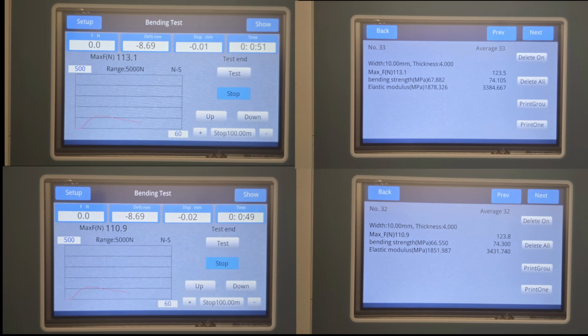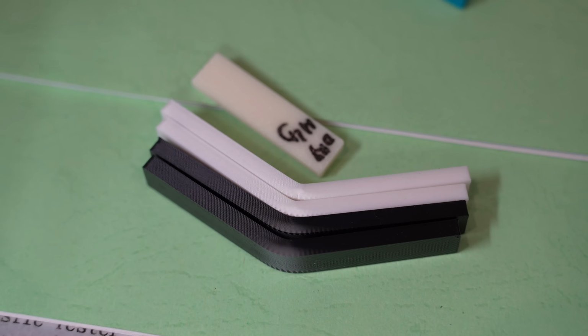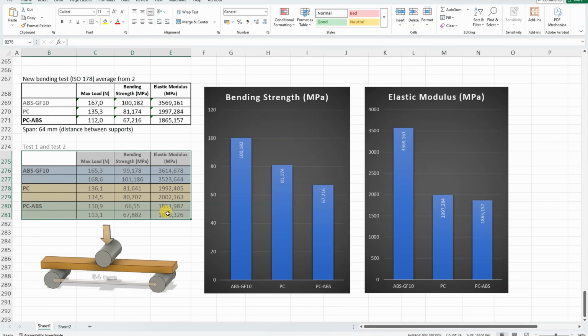And here you can see the maximum load, bending strength and elastic modulus, but also the graph of the break. Similar values from two measurings. These are measured numbers, this is the average from two. They're very close to each other, so in the future I will have only one test object in this experiment. The maximum load ratio is equal to the bending strength because it doesn't depend on the deformation, and that's presented on this graph, and the strongest is the ABS-GF.